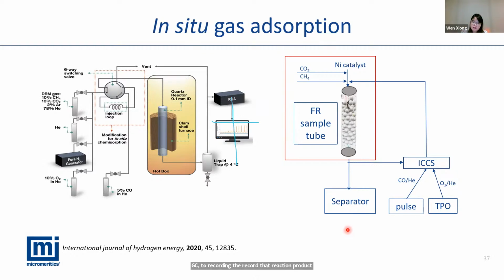And then after we do the reaction as we want and get enough kinetic data, we close the CO2 and the CH4 from the FR system, then switch back to the ICCS system. We introduce the oxygen from the ICCS, going through the sample to do the temperature program oxidation, to check the carbon deposition on the surface. We can also do the same thing by introducing CO or hydrogen from the ICCS, do the chemisorption on the nickel catalyst, and then check the nickel catalyst dispersion after reaction.